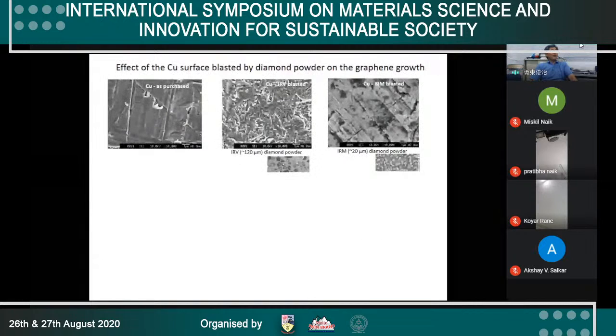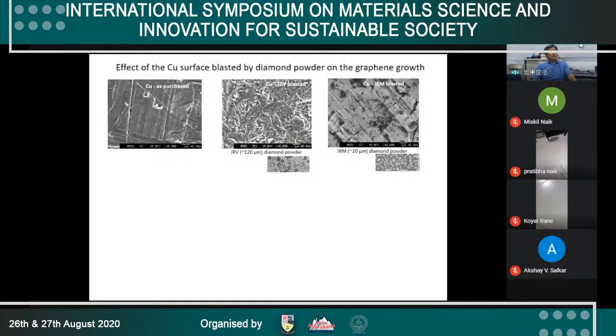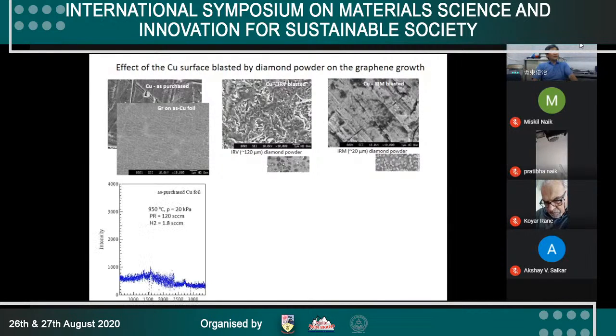This is the copper as purchased, the center is diamond powder blasted, and the right-hand side is also diamond powder blasted with a smaller size of diamond powder. After growing, the as-grown copper foil looks like this. This is the Raman result. Almost no graphene can be seen.